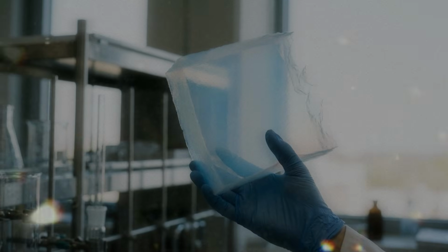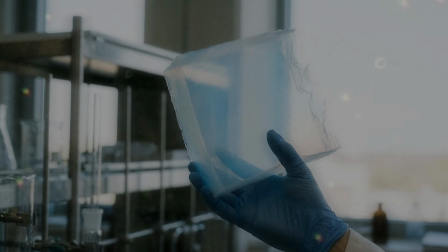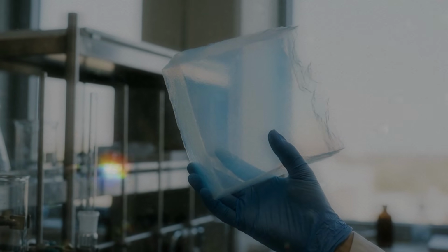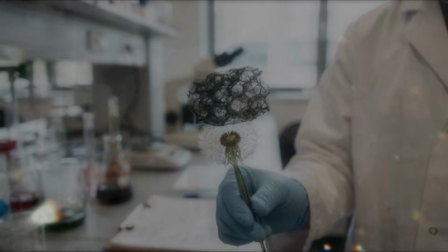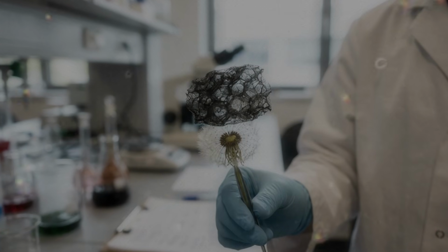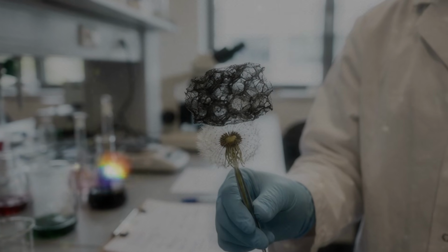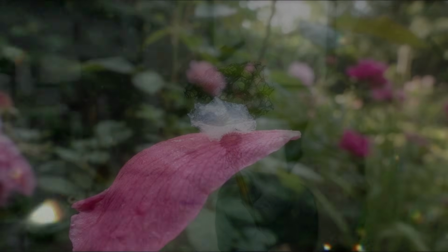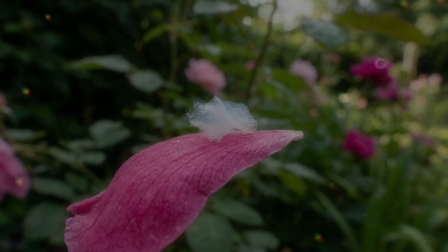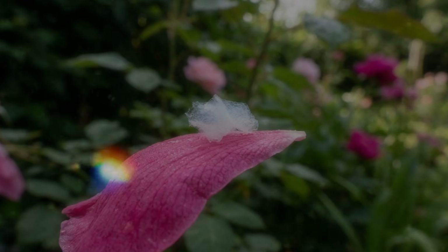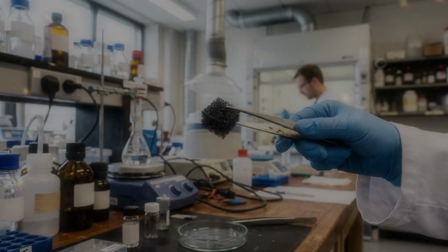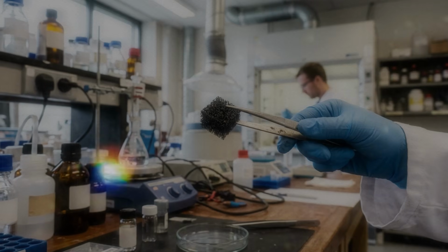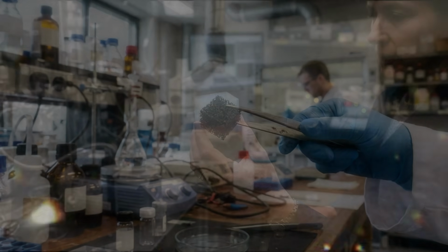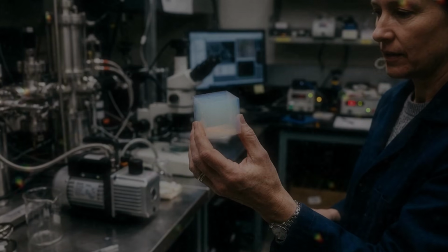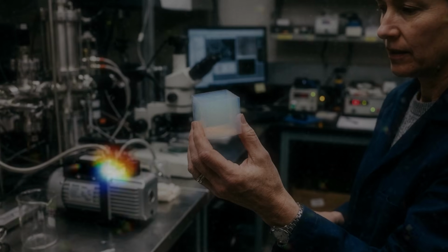Once the load is removed, they expand toward their earlier shape. In carefully designed materials, this recovery can continue through many repeated cycles. The sample does not recover because its empty spaces contain compressed springs. The walls themselves act as the springs. Folded graphene sheets bend. Carbon nanotubes flex. Connected cells collapse in a planned sequence. The structure stores some of the mechanical energy and releases it when the pressure disappears.